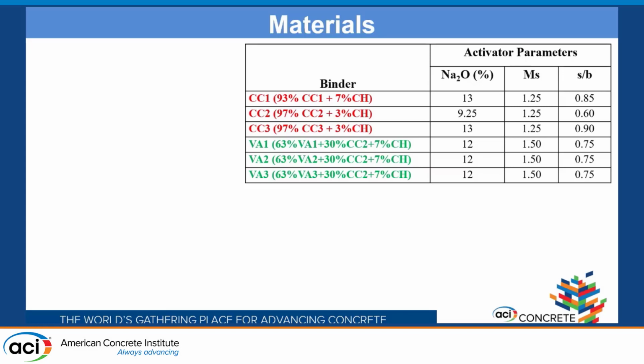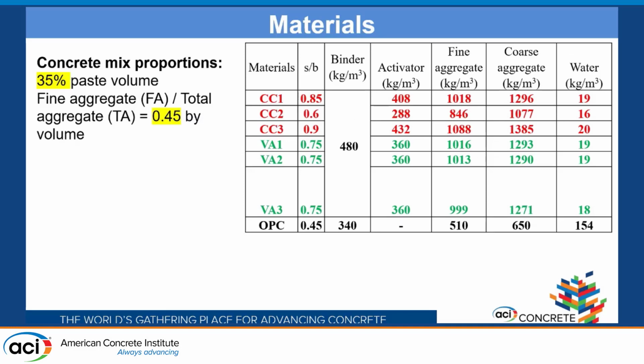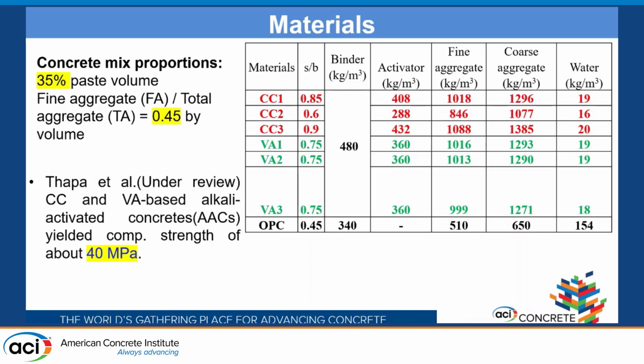Here you can see the activator parameters which are optimized for compressive strength. You can see the solution to binder ratio varying from 0.6 to 0.9. These are the concrete mix proportions which are used for this study. It is to be noted that all these concrete mix proportions have produced a minimum compressive strength of 40 MPa by the end of 28 days, and we have used OPC with a water to cement ratio of 0.45 to benchmark the performance of our alkali-activated concretes.